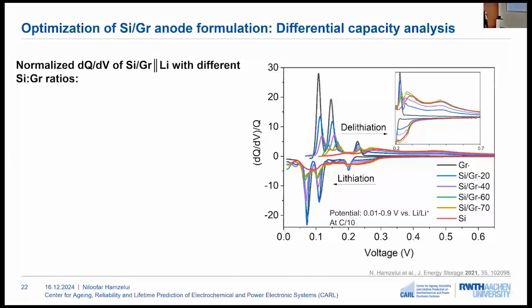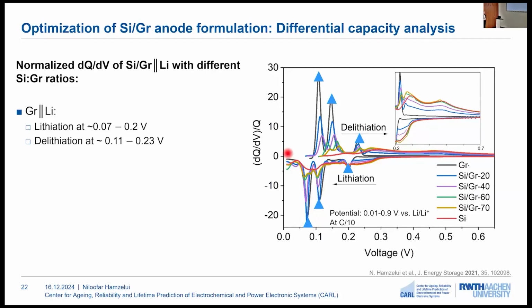Then the differential capacity analyses were performed on the electrodes with different silicon content, as well as pure graphite and pure silicon. Here we can see the normalized dQ/dV, and as can be observed for the graphite curve, the black curve, we can see the lithiation and delithiation peak, which is marked with the blue triangles. And we can see that by increasing the amount of silicon, the intensity of these graphite peaks is decreasing, as expected.